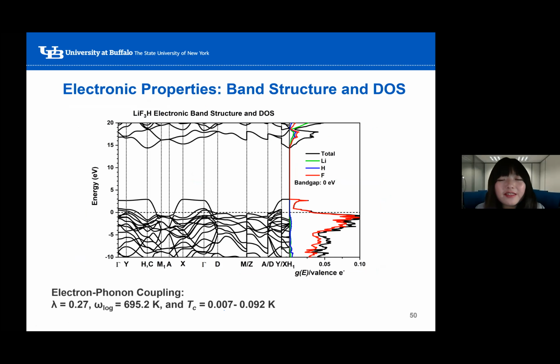5 out of these 6 structures are non-metallic. And the only one being metallic is lithium F3H. For the non-metallic phases, the band gaps are large, ranging from about 10 to 14 eV. This metallic structure at the Fermi level, its metallicity is mainly due to the F 2p characters, and it's not caused by the pressure-induced band broadening. Instead, it is based on the pressure-induced dissociation of the F2 molecules.